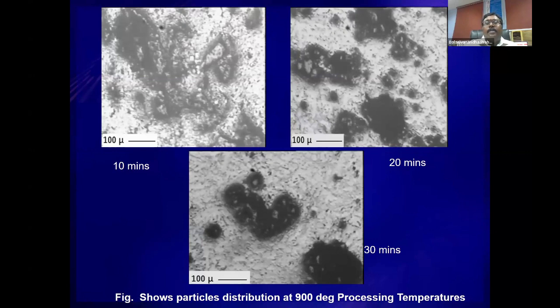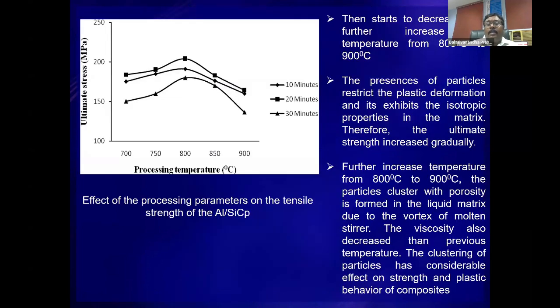So you have to have sufficient viscosity to allow the reinforcement to penetrate and then distribute uniformly. But if you have too low a viscosity, that allows the particles to settle down very quickly the moment you stop the process and before the casting. So that also makes more particle agglomeration. Therefore, an extremely low temperature is not favorable and a high temperature is also not favorable to have a homogeneous distribution of particles. That shows up in the mechanical properties also.